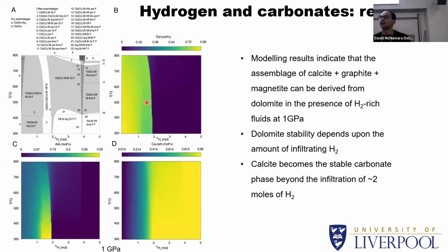So it's not just an instantaneous reaction that starts as soon as hydrogen infiltrates the system, but dolomite is a stable carbonate, and if you have 1 mole of hydrogen infiltrating your system, dolomite is fine. But as soon as you cross a threshold of about 2 moles of hydrogen, then you go from dolomite being your stable carbonate to calcite being your stable carbonate.